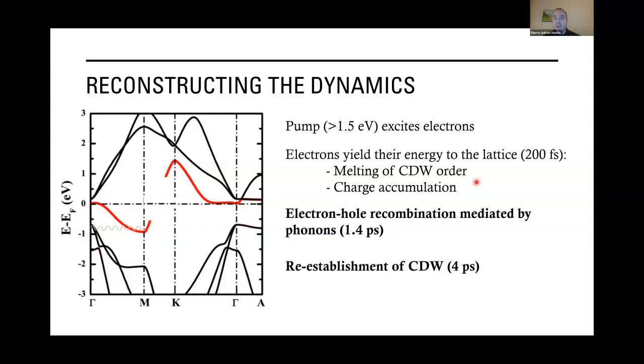And then on a longer time scale, we will have reestablishment of the charge density wave that is going to create a gap, and finally heat diffusion on a nanosecond time scale. So we have rebuilt the whole dynamic of the tantalum disulfide in this nearly commensurate charge density wave phase, and we have been able to get a unified picture with time-resolved ARPES that is really sensitive to the electronic structure, and time-resolved XRD and electron diffraction that are sensitive to the lattice.